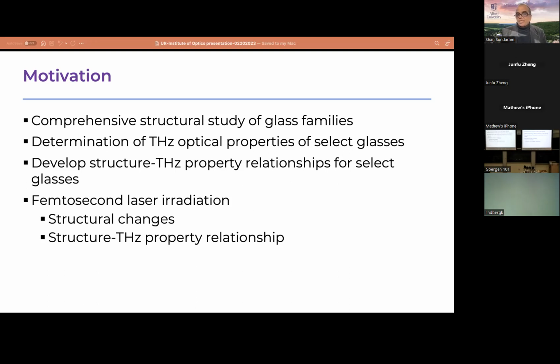By that, mainly I'm talking about refractive index and the absorption coefficient of these glasses, and collect data and then put together this structure-THz property relationship for select glass families, and present and also publish this work. We also did use femtosecond laser pulses to modify some of these glass compositions locally to see whether I can also change terahertz properties by using femtosecond pulse laser.